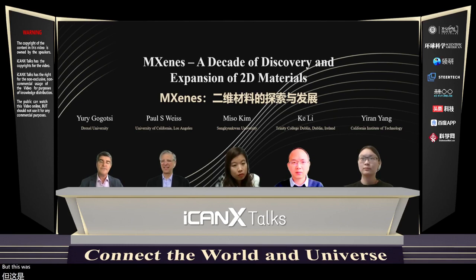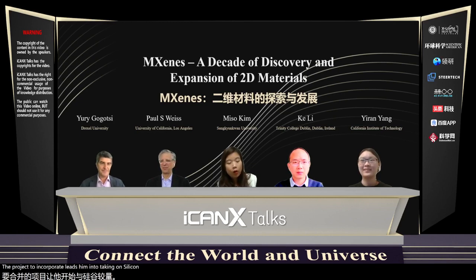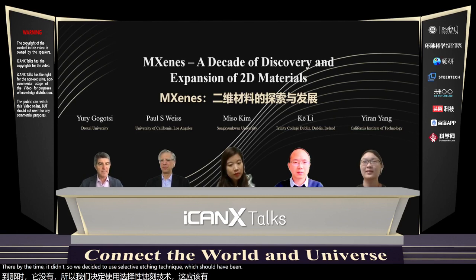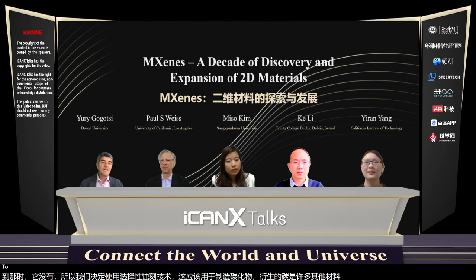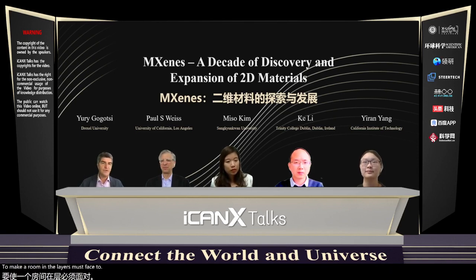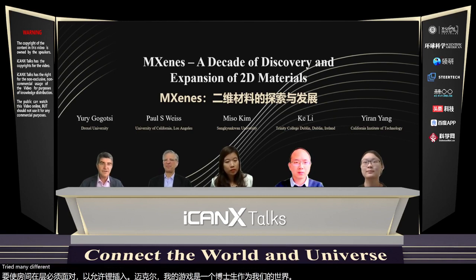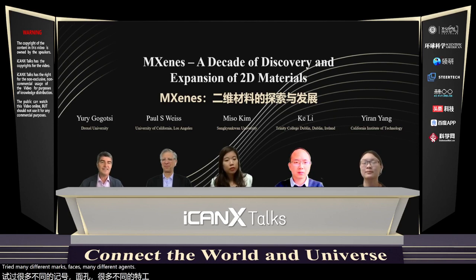But this was a combination of serendipity, luck, coincidence. We were actually working on a project to incorporate lithium into titanium silicon carbide MAX phase. And lithium refused to go in, even though our DFT prediction suggested that the energy barrier is not very high. We were able to accomplish it a few years later, but at that time it didn't work. So we decided to use the selective etching technique, which we have been using for making carbide-derived carbons and many other materials, to make room in the layers of MAX phase to allow lithium insertion. And Michael Naguib, who was a PhD student at the time, working with Michel Barsoum and myself, tried many different MAX phases, many different etchants, until he found that HF etched